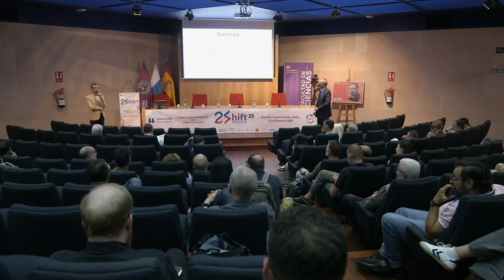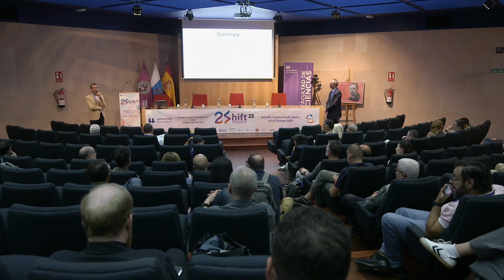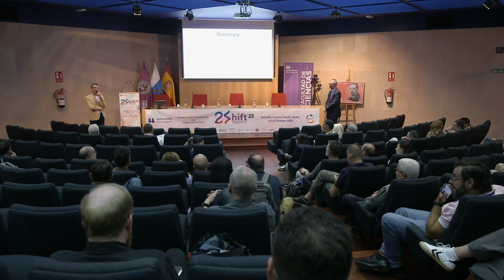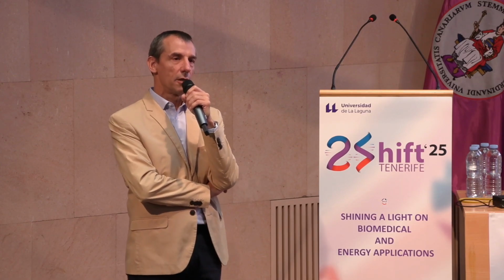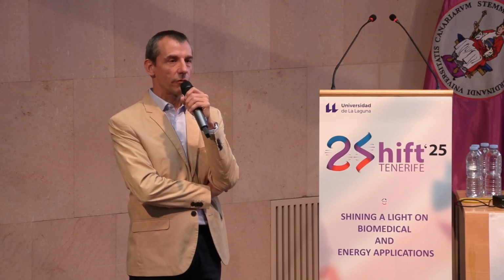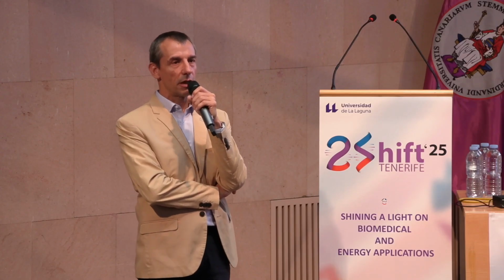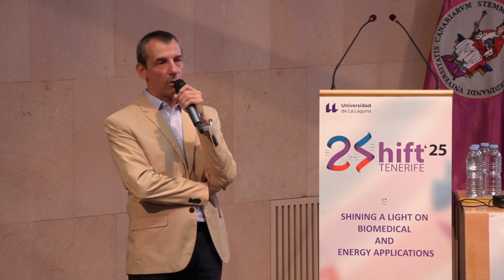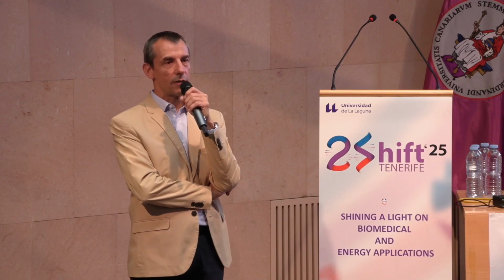It's, I would say, essentially, on the one hand, a big cryo generator like you may have, similar to what you have at 10K, but with more cooling power. So this initial system goes down to something like 3K. Then you can have circulation of helium at low pressure, which will get you to 1K. And then to go below that, you need to use helium-3 isotope. So it's a mixture of helium-4 and helium-3. You have a phase separation, which allows you to go to these milli-K.